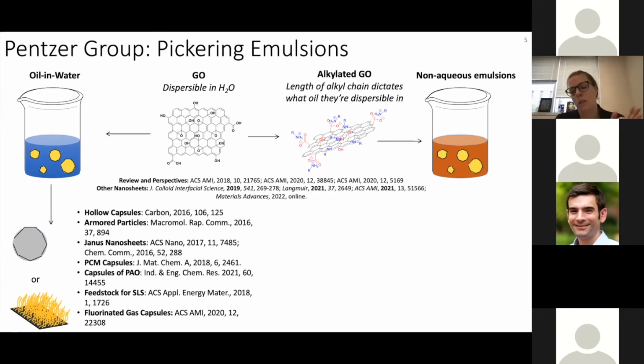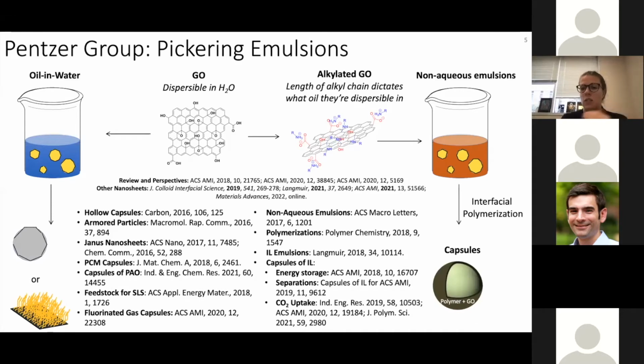So they're no longer dispersible in water. And depending on the length of the alkyl chain, they can be dispersible in different oil phases, from polar oils such as DMF to non-polar oils such as octane. And so this really gives us access to these non-aqueous emulsions.